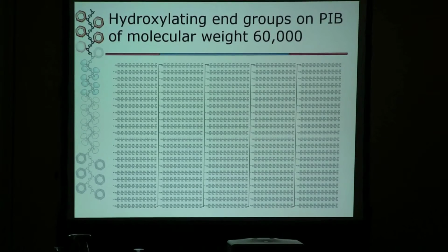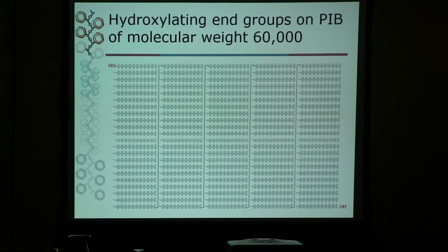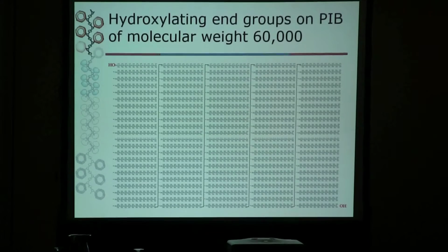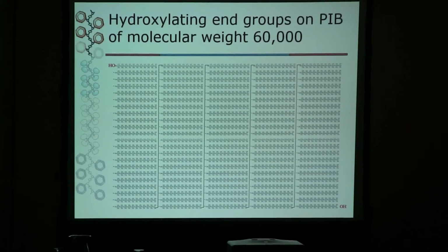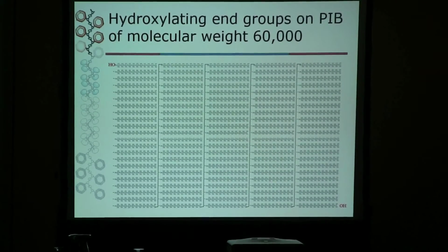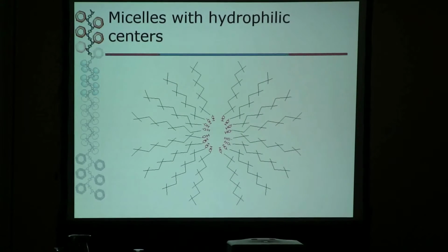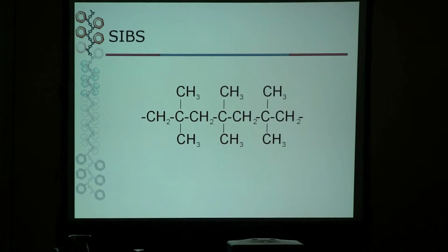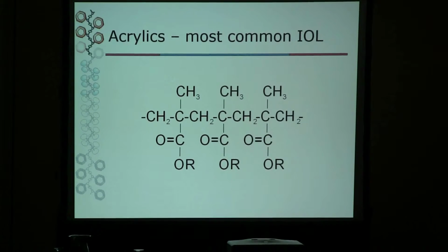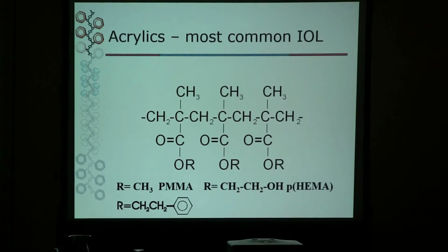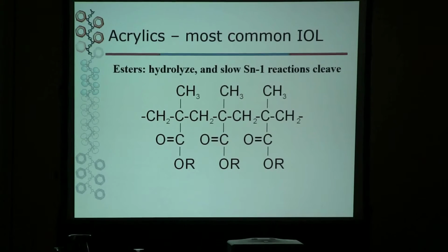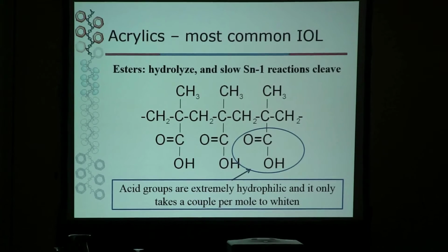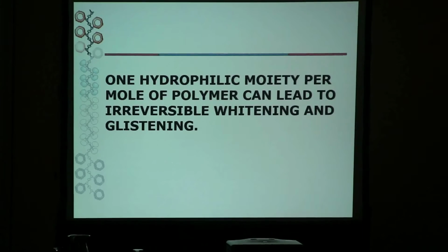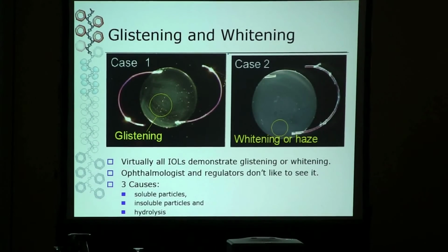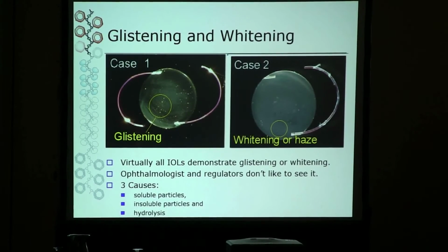Also, polymers tend to hydrolyze with time, and here you see the end groups. If you put an OH on SIBS, it'll turn it to white with water. So just 2 molecules in the molecular weight of 60,000 is enough to do that. So SIBS has no cleavable groups, but the acrylates do. And you know from organic chemistry that esters aren't stable in water. And they will tend to hydrolyze and you form the acid group. And this is another source of long-term whitening of intraocular lenses that occur. And it's irreversible. And this is what you see on the right. These were taken out of patients.